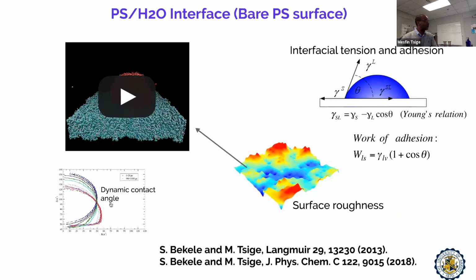So the benefit in our simulation is that we can follow how the contact angle is changing over time. This is more like a dynamic contact angle. And finally, when it saturates, we can go ahead and determine the contact angle. We can correlate that contact angle back to the interfacial tension between the liquid and the surface. And also we can calculate the work of adhesion with the information that we can gather.